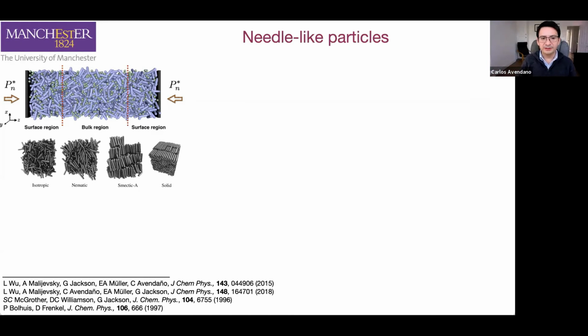There is a technique called the direct coexistence method, where you can actually put molecules or colloidal particles in a very elongated box like this one. And as soon as you have the conditions for phase separation, the phase separation will take place. That's a typical technique to obtain phase diagrams for mixtures of liquids and so on. However, for this kind of systems like cylinders and spheres in the colloidal regime, the problem is that if you use the same technique, you are not going to observe the segregation between two phases. Despite that thermodynamically you should observe that, it's not possible to observe that in reality. And the reason is because the surface tension of this system is so low that it's not possible to form a perfect interface between two phases that are being separated.